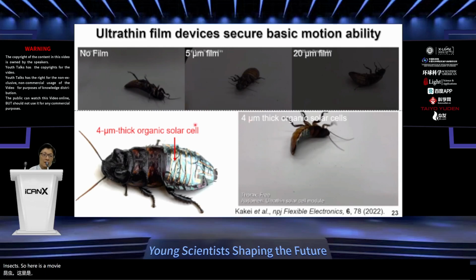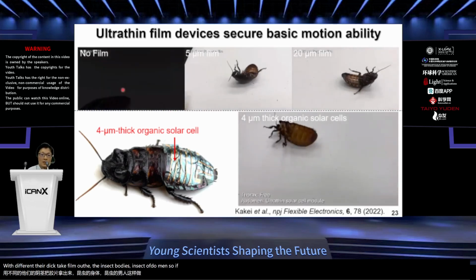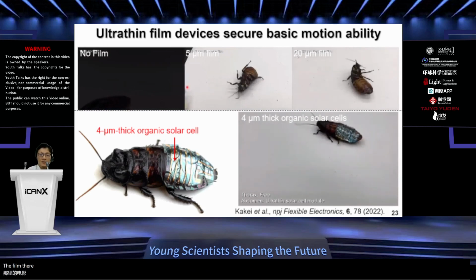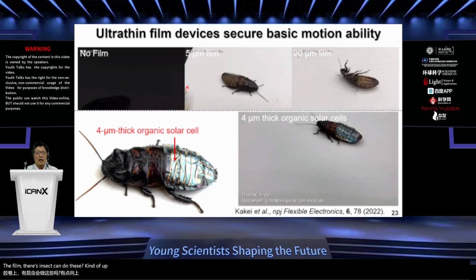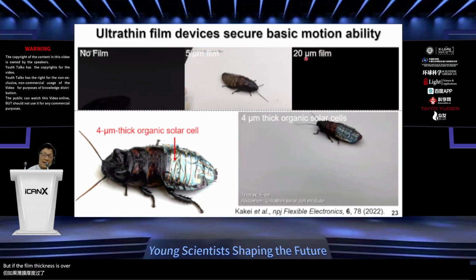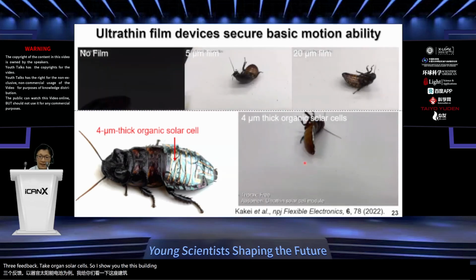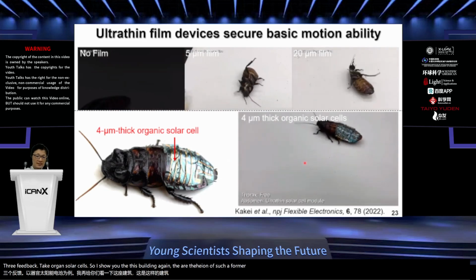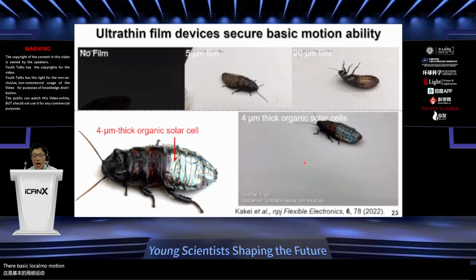So here is a movie clip with films of different thicknesses adhered onto the insect abdomen. If we use a sufficiently thin film, the insect can do this kind of upside-down self-righting movement. But if the film thickness is over 10 microns, the insect cannot do this self-righting attempt. This is very important because fortunately we fabricated 4 micron thick and 3 micron thick organic solar cells. So I show you this video again. The adhesion of such 4 micron thick organic solar cells does not interfere with the basic motion ability of this insect.